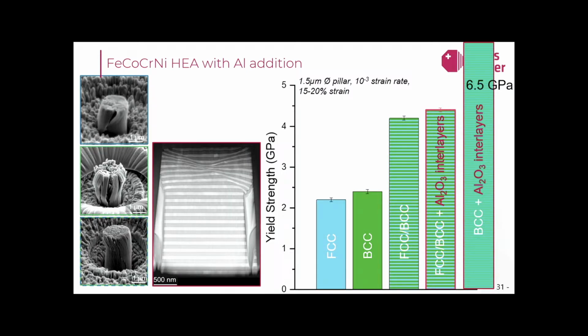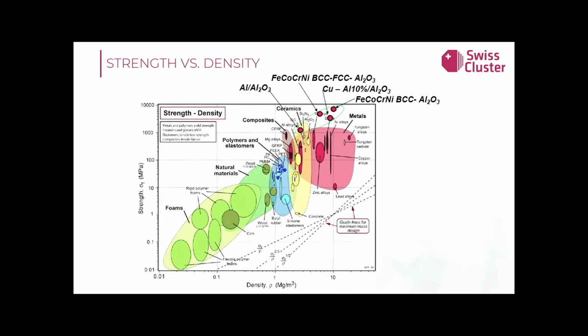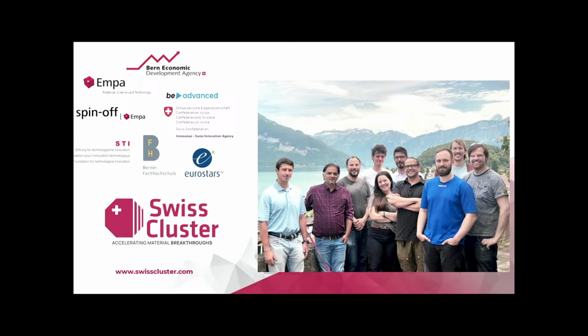We, of course, also tried with just BCC. We obtained probably one of the hardest metals, which is also very plastic, of 6.5 gigapascal. So this is actually quite high. And if we put together all of the material combinations that we have done in this type of system, in a one-step process, in our SE1, we see in the Ashby plot that we are already above what has been reported in literature for this type of material chemistry. So yeah, I hope that with these few examples, I was able to show that ALD and PVD has a very nice effect that can be used for different applications.